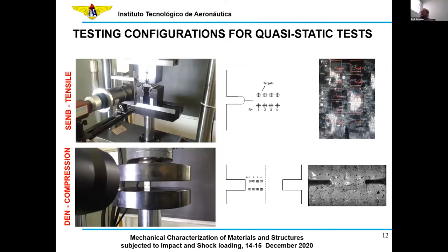As I already mentioned about the standards, we have no standards for data reduction for the determination of the strain energy release rate for composites, for the intralaminar fracture toughness of composites, right? Therefore, we have to find a way to measure that directly. And the way we actually use here for measuring directly the strain energy release rate or the stress intensity factor was by using digital image correlation.